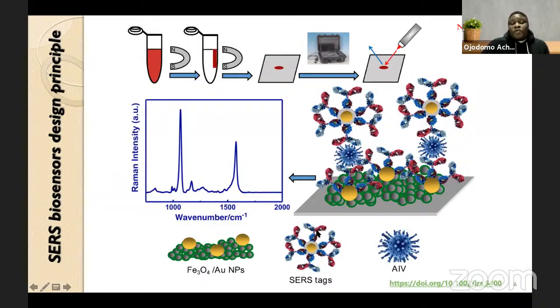Then, in order for you to bring the SERS nanotags closer to capture your analytes, you need a biotargeting agent, which in this case is an antibody. So what happens in this system typically is that you can have a solid substrate, shown here, where you can carry out your Raman measurements. This substrate was functionalized with magnetic gold nanoparticles to aid magnetic separation, just like what you see here.